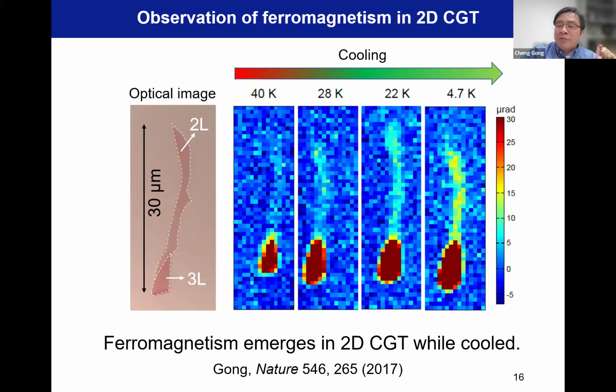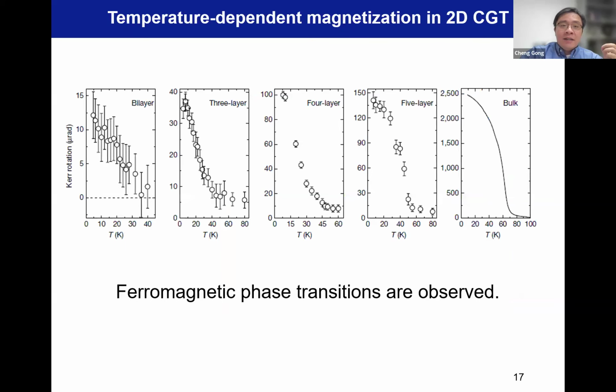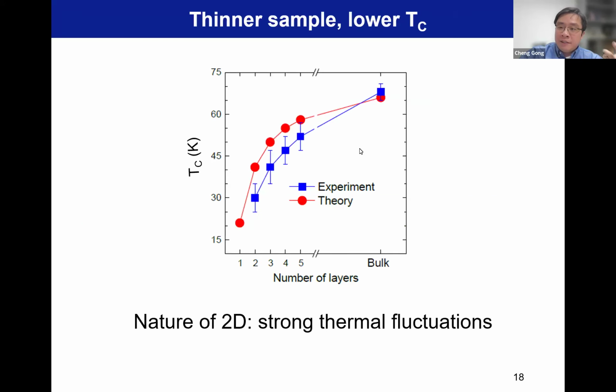And this is also one reason why it was so hard to observe 2D magnets in early days, because they have a reduced TC. And meanwhile, of course, the small volume sample will give limited signal strength. Anyhow, we did a systematic thickness dependent, temperature dependent Kerr rotation measurement, and then you can extract the onset of the Kerr rotation angle and define it as the TC. So you can see a thickness dependent TC.